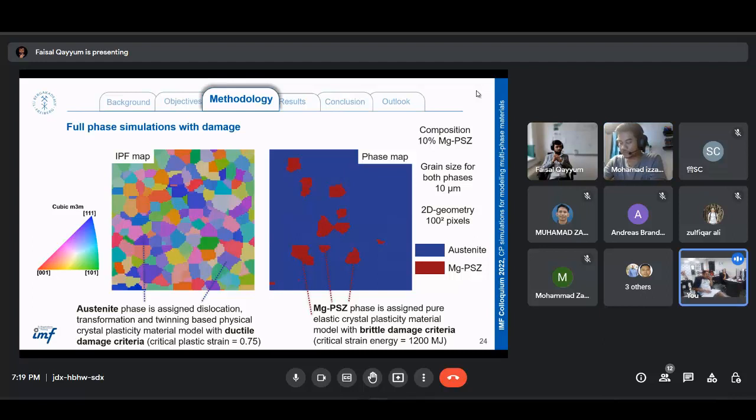So Faisal, does the voxel represent the grain or not actually? It can, if the voxel is basically a small piece, a finite element where we are breaking one big grain into small components, which we are calling solution points or voxels, and it can represent one grain if the resolution is very low. Do you understand that? But a grain can also comprise several voxels which have the same orientation distribution, same phase, same attributes assigned to them. So then it would be one big grain, as we can see in the slide.